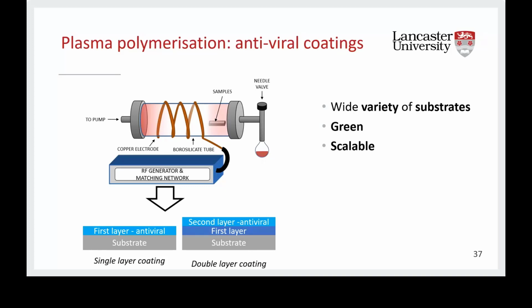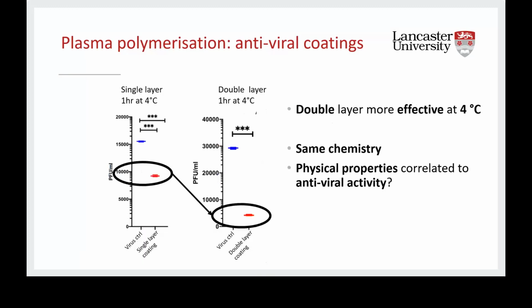In this research, we are comparing two different configurations called the single layer coating and the double layer coating. In the single layer coatings, the substrate is coated by a layer of antiviral plasma polymer. While in the double layer, first we coated the substrate with a layer of non-antiviral plasma polymer, and on top of this layer, we deposited the same antiviral plasma polymer. And we tested them against COVID-19. Actually, they are all effective against COVID-19, but interestingly, the double layer is more effective at 4 degrees Celsius with respect to the single layer.